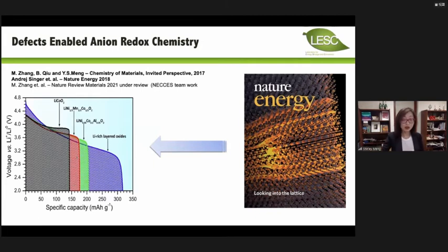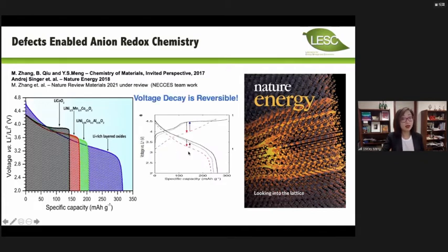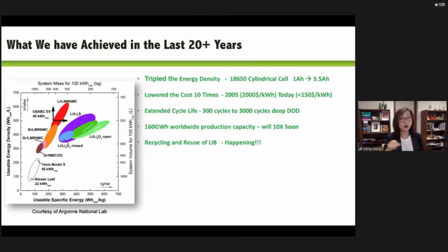I mean, it was widely criticized that this material has a voltage fading problem. But right now, I think this voltage problem is completely under control, because we now understand defects play a very important role in the voltage decay. By controlling the defect density, we can actually control the voltage decay, and we can predict the voltage decay.